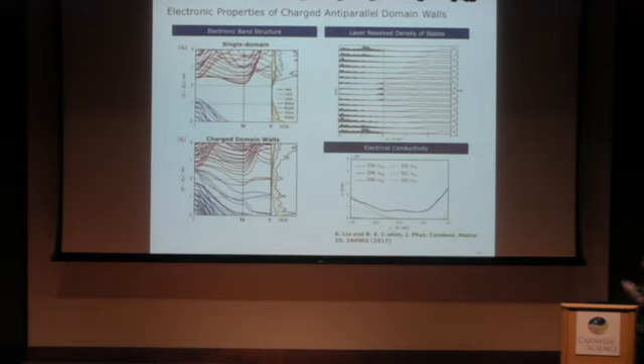We further look at the electronic structures of charged domain walls. What's happening is the presence of charged domain walls closes the band gap. You may think the system is metallic. Well, you may say it's a polar metal, but from the layer-resolved density of states, we can see that we have quasi-two-dimensional localized electrons at the head-to-head domain wall and also a quasi-two-dimensional hole gas localized at the tail-to-tail domain wall. So these free carriers almost compensate the polarization bound charge perfectly, therefore screening the depolarization field.